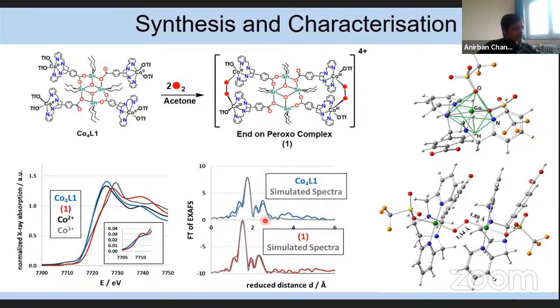So from the EXAFS parameters and the DFT calculation, we optimized the geometry of the tetranuclear cobalt complex, where the cobalt center is coordinated with 4 nitrogen and 2 triflate, so it's a 6-coordinate. However, when reacting with oxygen, it becomes a 5-coordinated species. As you can see, one of the nitrogen atoms is not binding with the cobalt center, and this is the energy-optimized model in the DFT. And in the peroxo species, the O-O bond distance is around 1.34 angstrom.